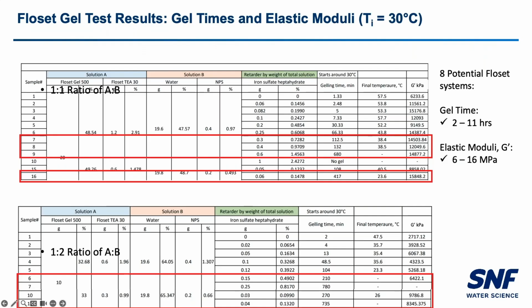So this just shows some of the initial testing that we did at 30 degrees Celsius at 1-to-1 ratio of the two components and 1-to-2 ratio of the two solutions. Out of this initial data, just focusing on gel time for the most part, we see maybe 8 potential Floset systems. So there's 1, 2, 3, about 4 from the 1-to-1 ratio and 4 that we feel in the 1-to-2 ratio. You can see the gel times range from 112 minutes, roughly 2 hours, up to about 11 hours, 735 minutes there. So pretty reasonable range in terms of time to not only mix, but get it down to the bottom of the wellbore, possibly recirculate back up the backside of the annulus.